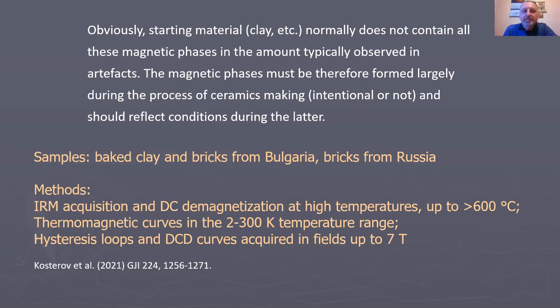And the methods we used, apart from the standard rock magnetic methods, were the IRM acquisition and DC demagnetization curves measured at high temperatures, up to above 600, but it depended on the sample, of course. Also, we measured some magnetic curves in the cryogenic temperature range from 2 Kelvin to room temperature, and also acquired the hysteresis loops and DCD curves in fields up to seven Tesla, which is essential when working with ceramics.